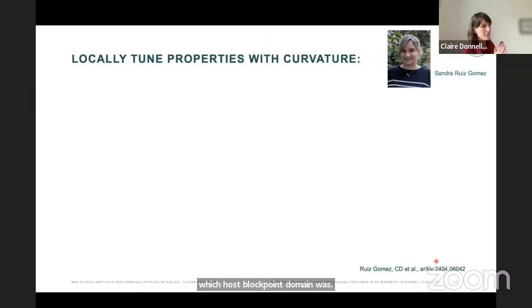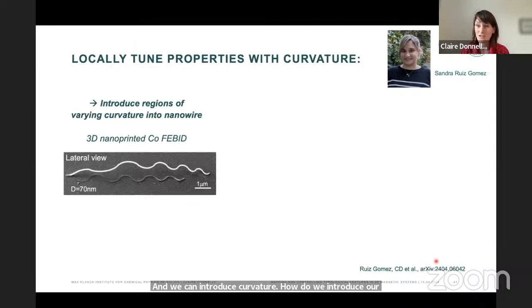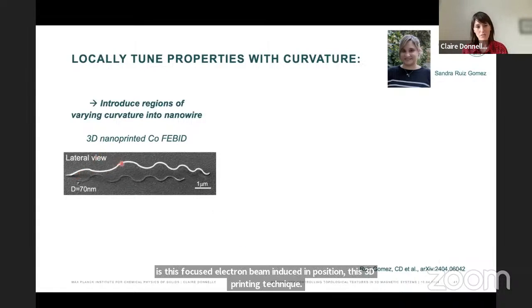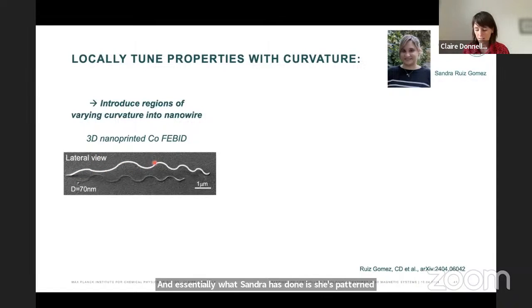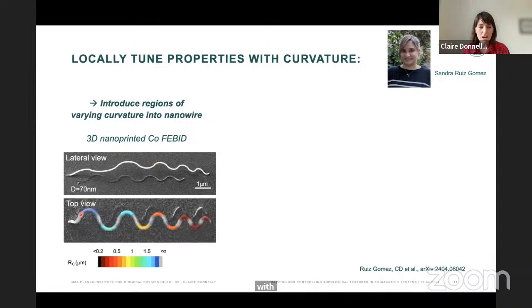Now, how do we introduce our curvature? Well, we again use the same technique, which is this focused electron beam induced deposition, this 3D printing technique. And essentially what Sandra has done is she's patterned with FEBID a nanowire which has a varying curvature, which is very nicely defined by the CAD file that she initially designs, where we have lower curvature on the left-hand side and higher curvature on the right-hand side.